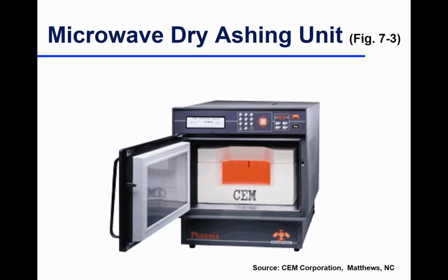The dry ashing is also a microwave dry ashing furnace where you heat by microwave, and it can go up to 1000 degrees Celsius. So it can go up to high temperature, and again, analysis time can be 20 minutes, 30 minutes, or 40 minutes, depending on the sample you're trying to combust. And it's pretty good, gives you very comparable results to a regular muffle furnace.